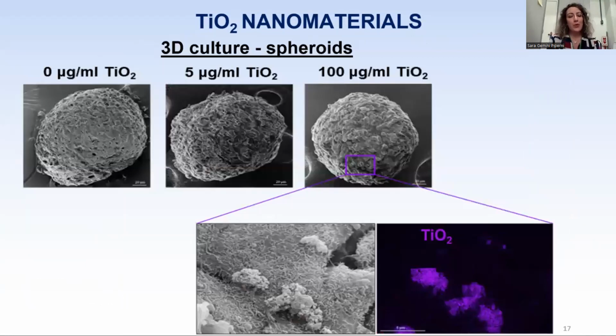Then we started to work with the 3D cell model to compare what happened in this model compared with the monolayer. So we formed a spheroid culture, and then we exposed this model to different titanium concentrations. Scanning electron microscope was coupled with energy dispersive X-ray spectroscopy, and this permits element identification based on atomic structure. So we show that the spheroid's morphology is not compromised by the titanium interaction.